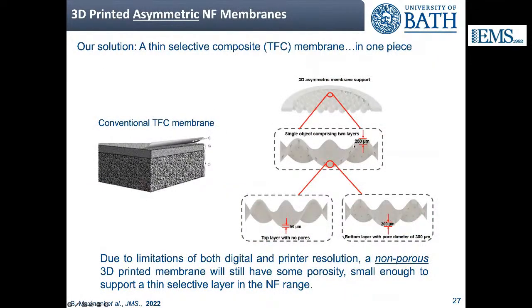So what we did is we manipulated the CAD file for the top part of this single 3D printed object to have no designed pore, but to still have some porosity that is small enough to support a selective layer in the nanofiltration range. So just to reiterate, this is a single object that has a bottom part with designed large pores of 300 micron, and the top part which has no designed porosity, but still has some porosity coming from the way we manipulated the 3D printed digital file.